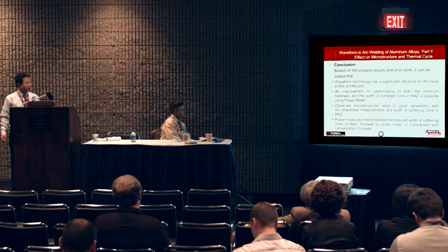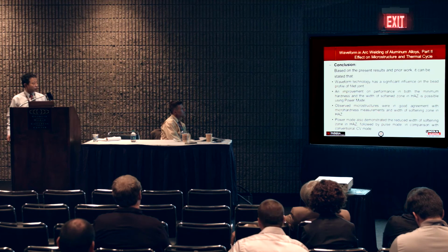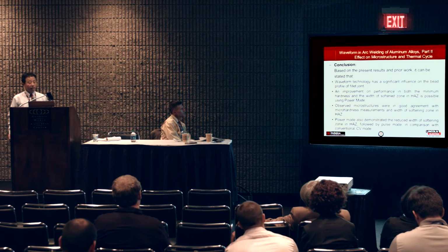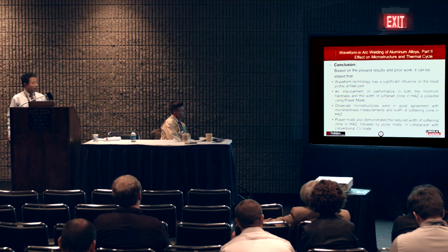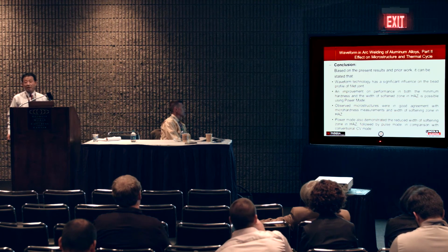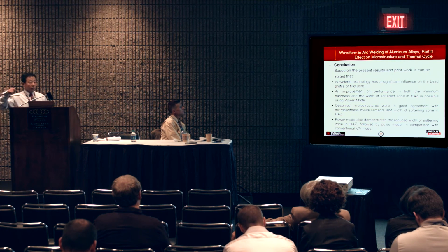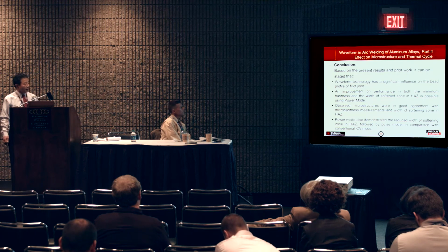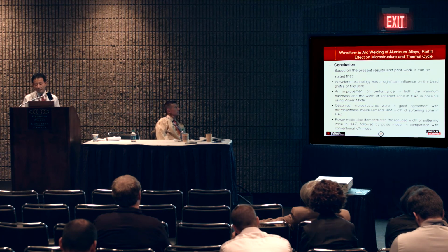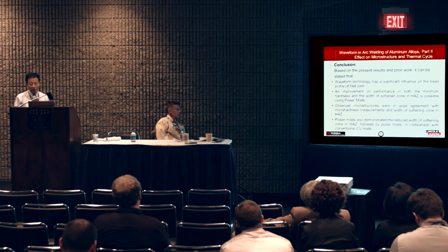And the third point is that the observed microstructures were in very good agreement with the microhardness measurement and the width of the softening zone in the heat affected zone, which I showed you in a previous slide. The last point is that the power mode has demonstrated the reduced width of the softening zone in the heat affected zone, followed by the pulse mode, in comparison with the conventional CV mode.